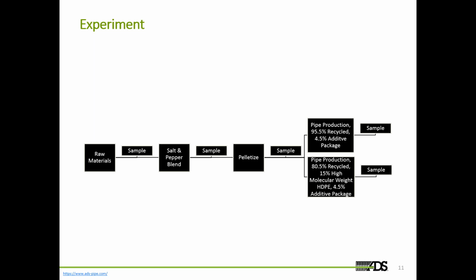So again, we're looking at those stage 2 failures through stress cracking that HDPE is prone to, and we're trying to look at, A, are we hitting the minimum stress crack values that are required under the AASHTO specification, and B, when we're looking at the UCLS test, is to make sure that we're not getting any contaminants in our pipe through our processing of our post-industrial and post-consumer recycled material.